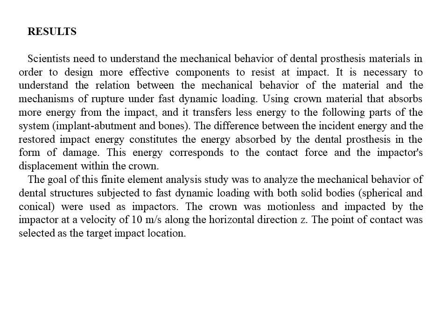The difference between the incident energy and the restored impact energy constitutes the energy absorbed by the dental prosthesis in the form of damage. This energy corresponds to the contact force and the impactor's displacement within the crown.